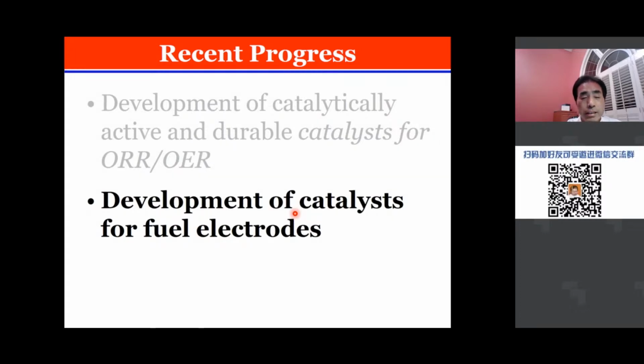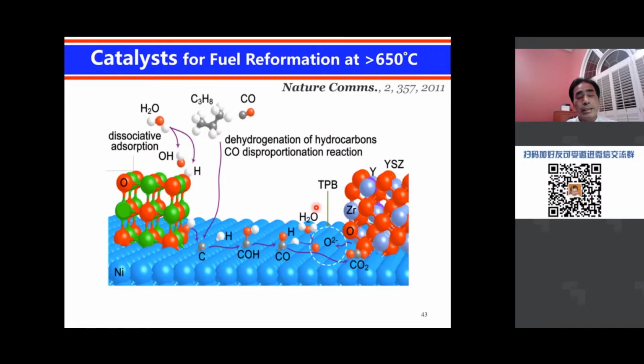So that's the progress in the air electrode. Now next, let me just quickly mention a few things about the second aspect, the development of catalysts for the fuel electrode. Here, if we're going to use hydrocarbon fuel without a separate reformer, we're going to bring hydrocarbon molecules directly to the anode of the solid oxide fuel cell, then there must be a mechanism for removal of carbon, because carbon is going to form on the surface. Unless there's a way you can remove carbon, coking is going to be the problem.